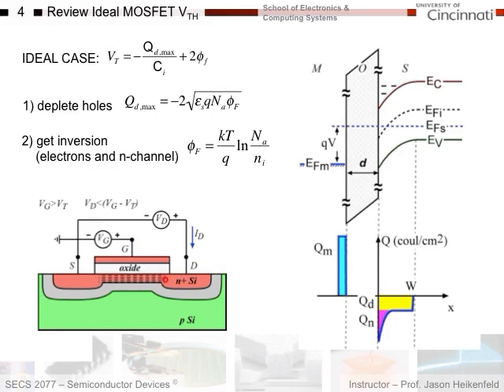The second thing we had to do is we had to basically shift the bands at the interface such that the interface now looks as N-type as it was previously P-type. So if we have this much offset here, meaning below the intrinsic level, it's this much P-type at the interface, we're going to have this dip below this line by that amount or more. And how you measure that, if this was phi sub F, then we need 2 phi sub F. We have to go 1, 2 to shift it to N-type material. So 2 phi sub F, and that's easy to calculate as well. Okay? So that's where we left off.